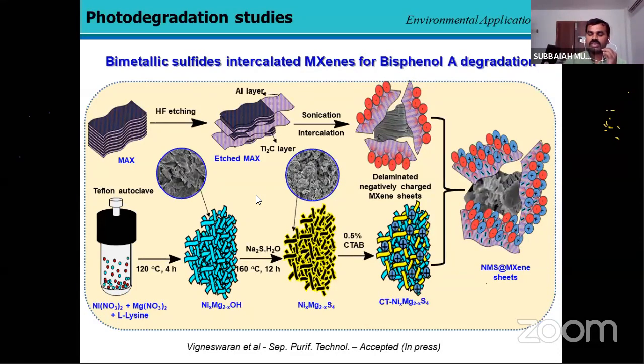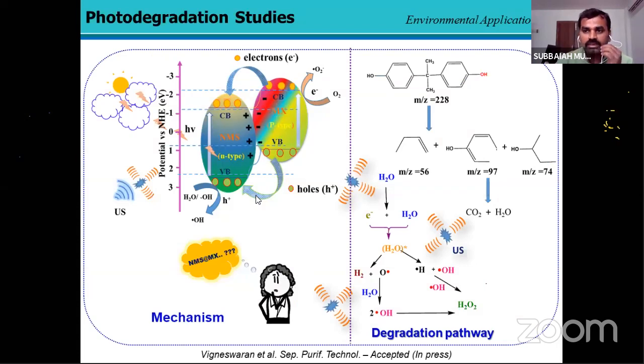Sulfur is more beneficial for degrading other materials, also due to its electronegativity. Then this material was combined with the help of some surfactant. We found that this material is highly effective at degrading bisphenol A. This was confirmed by the ESR results. Then this paper was accepted. This is the main mechanism behind how bisphenol A is degraded.